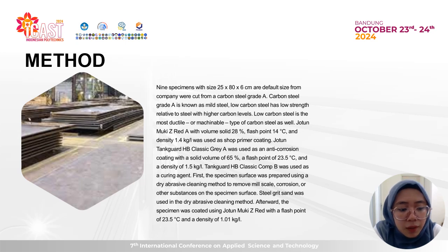Based on this problem, the author analyzed the addition of Jotun Tankguard HB Classic anti-corrosion paint in 3 different primer deposit conditions: material without any subprimer or 0%, and 50% and 100% subprimer remaining. The test determined how important the subprimer's influence is on the addition of the Jotun Tankguard HB Classic anti-corrosion paint to the fuel oil tank materials. The material preparation is 9 specimens with size 25 times 80 times 6 centimeters, the default size from the company, cut from carbon steel grade A. Carbon steel grade A is known as mild steel.